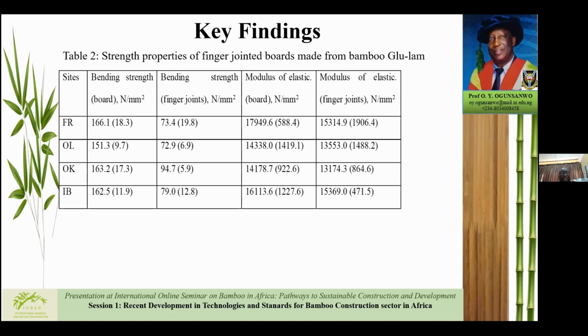We look at strength properties of a finger jointed board made from glulam. The result in table 2 is giving us, for instance, the samples obtained from FR, 166 Newton per mm square, and then 73.4 in the finger jointed, meaning that the finger jointed bamboo is weaker, but it gives opportunity for unlimited length when we are trying to use bamboo for wall cladding, for instance. So we can manipulate it to a very long length in terms of utilization, because we are trying to prepare people to produce bamboo that is going to be meaningful and useful in the market.